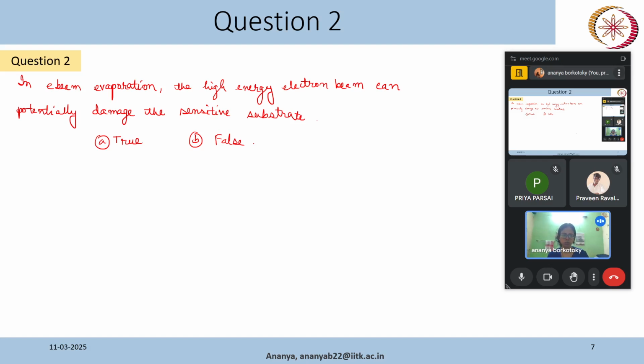This is what we observed when we tried e-beam evaporation on a patterned wafer. When the pattern was done using some photoresist, the photoresist became so hard that it was so difficult to remove. Okay, so this cross-linking kind of problem happened.